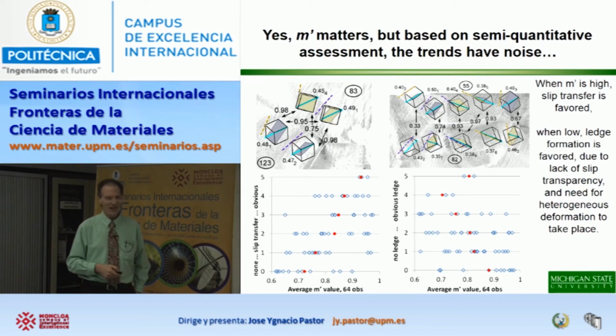But we can still take averages, and we can see things that make sense. So if I see slip transfer, you can see some features like this that go right on through this grain boundary. Then I can say there's some obvious slip transfer. In other cases, I don't, such as here. I don't see slip transfer. In fact, I see a ledge developing, and there's nothing. It doesn't pass through here quite so nicely.